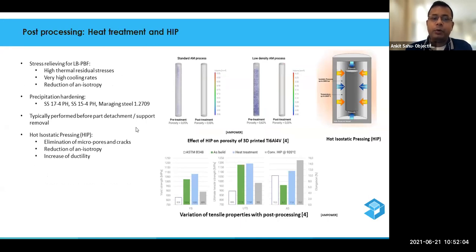So these are some of the post-processing heat treatment requirements, because we should understand why heat treatment is required and why hot isostatic pressing is really common in additive manufacturing. The component produced by additive manufacturing has really high thermal residual stresses, and it involves very high cooling rates. So there is a reduction in anisotropy, and precipitate hardening is also a requirement in some alloys, such as 17-4 PH, 15-4 PH, and maraging steel. So some kind of microstructural changes are required for the enhancement of the properties of the material itself.